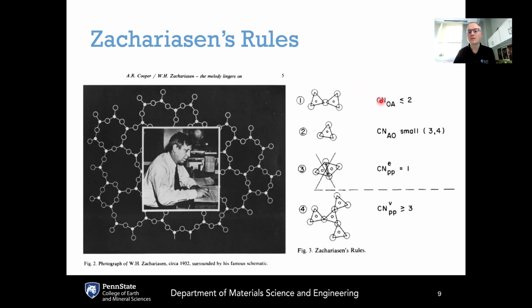Here, this is that the coordination number of the cations around the oxygen is less than or equal to 2. So here, if you look at this oxygen, it is being shared at these 2 corners of the polyhedron. And you'll see that the oxygen is coordinated to 1 of the cations here in the center of this polyhedron, and then a second cation here in the center of this other polyhedron. So the coordination number of the cations A around the oxygen is less than or equal to 2.